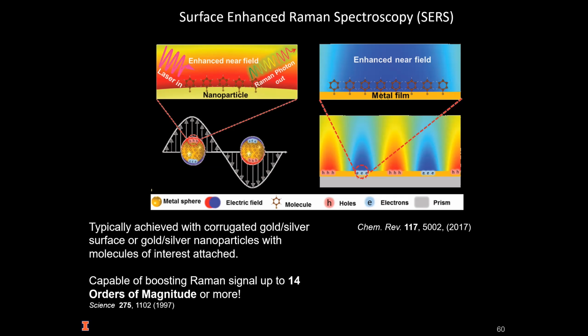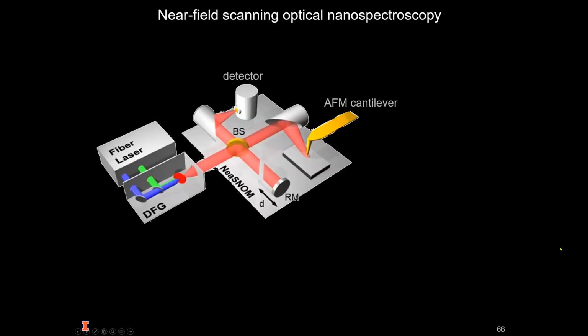Then there's what we call tip enhanced spectroscopy. Also, you need a very, very flat sample. In the case of our spectrometer here, you need samples that don't have peak to valley depth more than 2 microns, to be able to put it in the microscope, including the tilt of the sample.